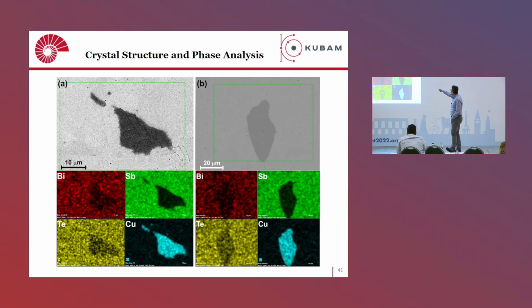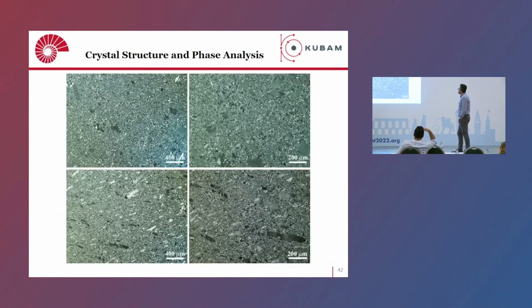You can see that this is copper telluride, and the rest is bismuth antimony telluride. So these are the optical images. These two are the cross-plane direction, and this is the in-plane direction. There is a striking difference between them. In the in-plane direction, we just see very nice layers of bismuth antimony telluride, which means the main orientation is towards the in-plane direction.